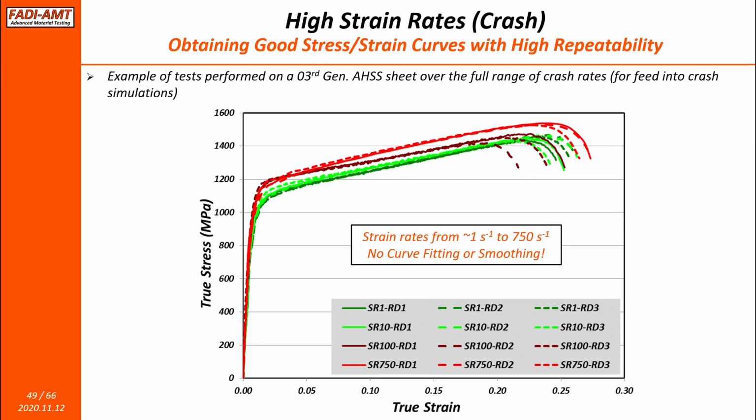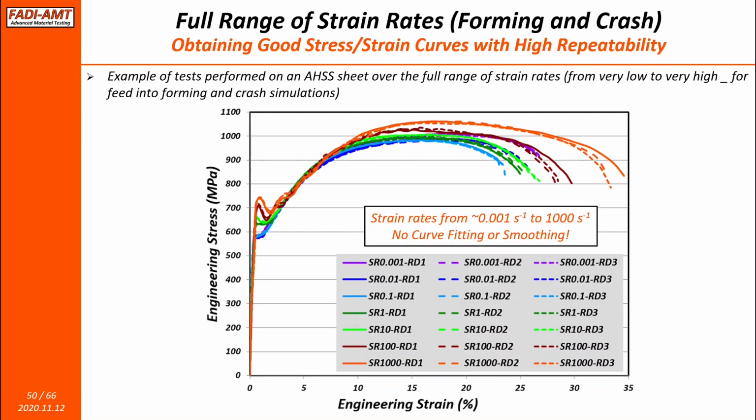Another set of curves at higher rates. This is a set of curves that was generated for a material that was used for crash applications or crash simulations. And the deformation rate went from, or we covered it from 1 to about 750 strains per second.